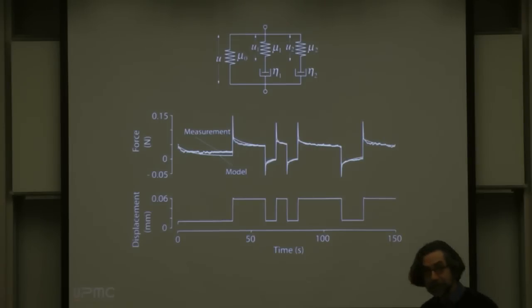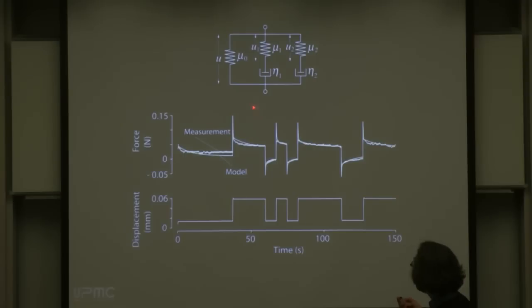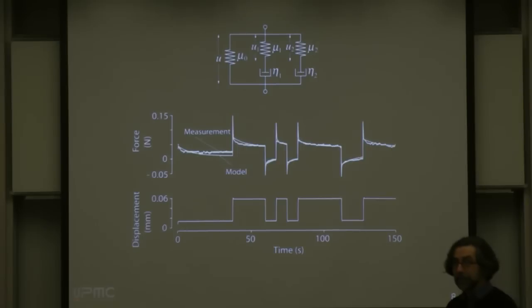And then in the dynamic domain, the skin that you have in the fingers, as I said, is not a simple elastic material. It's viscoelastic, and it's classically described by two time constants in tissues. One is super fast, so if you apply a sudden displacement to the skin, you get this spike of force, because it has a very short time constant. It vanishes very quickly, and then you have a second one here. So there are at least two time constants in the skin.